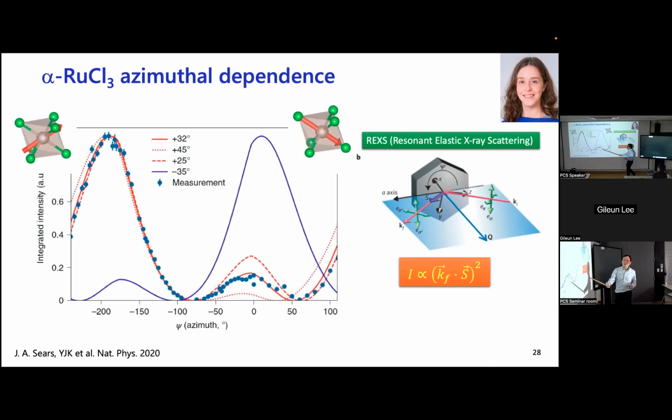And we have done that measurement, and then you can fit this into these different types of models. And this is a completely geometric, so this is not a complicated fitting. Based on this, you can easily figure out the angle between the spins and the honeycomb plane matches really well with about 35 degrees in this geometry instead of that geometry.